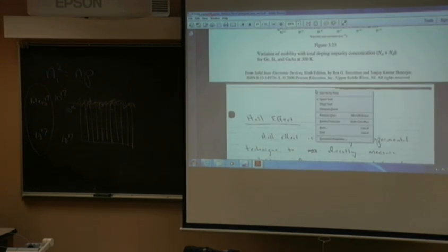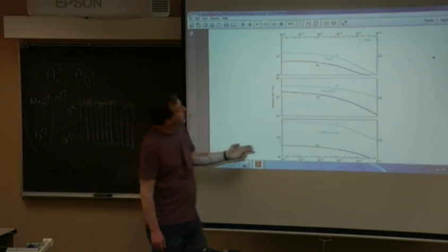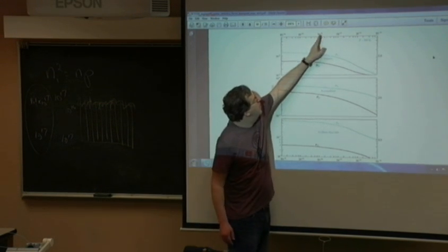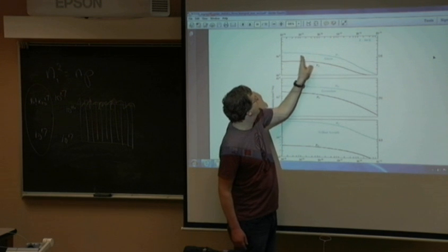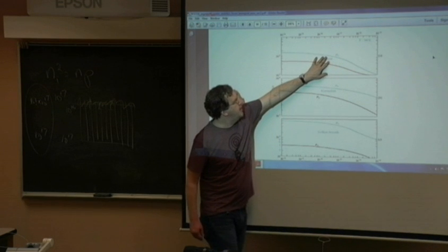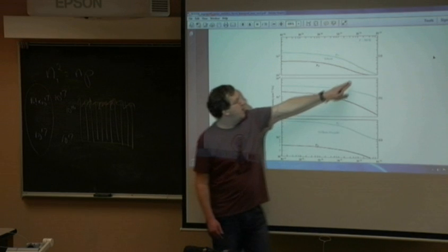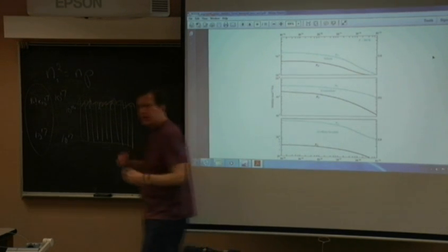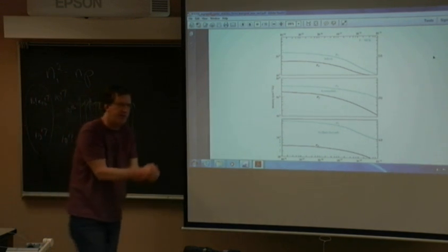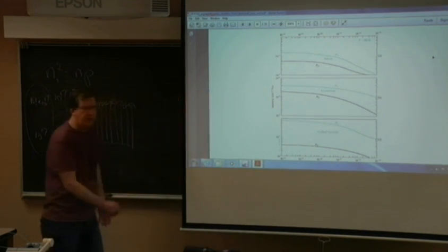and you're probably going to have to make a PN junction and dope it. So therefore, the silicon, which one's silicon? Silicon's this one. If I dope it to something mid-range, 10 to the 16, 10 to the 17, my mobility is sagged because I have impurity scattering that's slowing things down. And if I dope it really highly to have that transistor move a lot of charge, my mobility really drops. It's like the finish line gets farther away. The more doping I put in to make it better, the harder it gets to push the charge through because the mobility drops.